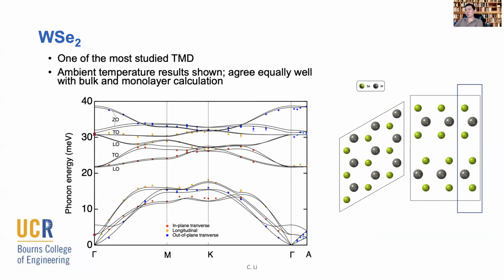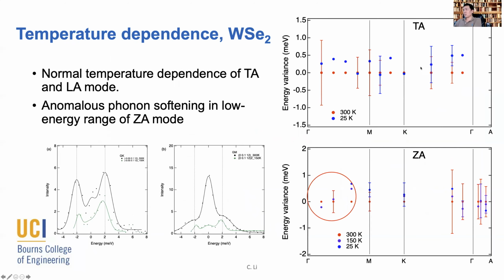The van der Waals interactions are quite weak between the layers, and it's the pressure that is going to tune it more covalent-like. But before you apply pressure, it's very weakly bonded, and you can almost understand the monolayer lattice dynamics properties by looking at the bulk. So here's what we are trying to do in this system. On the right-hand side, I'm showing some of the temperature dependence results. There is a clear stiffening of the transverse optical mode and acoustic mode as you decrease the temperature. The data is still kind of scattered all over the place. That's mostly because for some of the points, especially the high energy points, our energy resolution is relatively coarse.